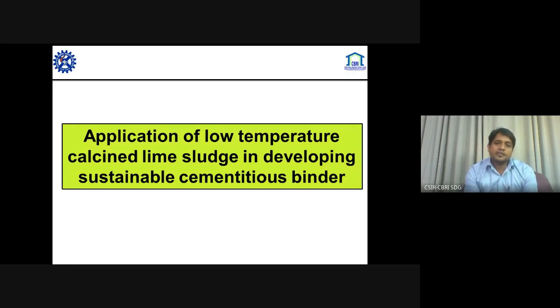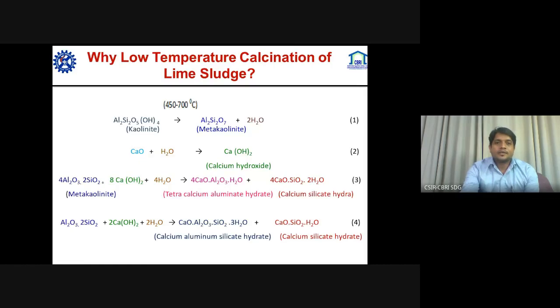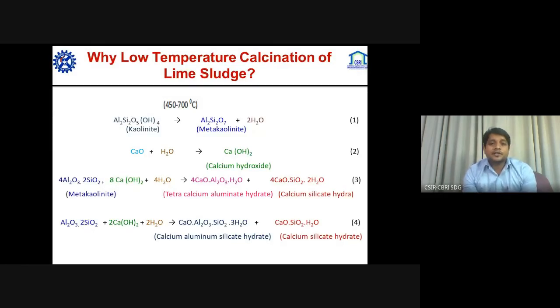I'm taking the third objective: application of low temperature calcined lime sludge in developing sustainable cementitious binder. Why is low temperature calcination of lime sludge required? Because at a temperature of 450 to 700 degrees C, kaolinite is converted to metakaolinite. The kaolinite is present in lime sludge at 5 to 10%, and when we convert it to metakaolinite, it is a pozzolanic material, and this pozzolanic material will react with the calcium hydroxide, which will form tetracalcium aluminum hydrate and calcium silicate hydrate, which is CSH gel, and it will further develop more CSH gel, which will enhance the compressive strength of the concrete.